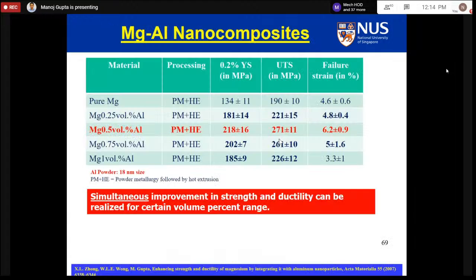For example, you can even reinforce magnesium with another metal element like aluminum, and you can increase the strength from 134 to 218, about 63% improvement. UTS you can improve by about 42%, and you also improve the ductility to 1.5 times roughly. Simultaneous improvement in the strength and ductility is possible only when you use a nano length scale reinforcement.